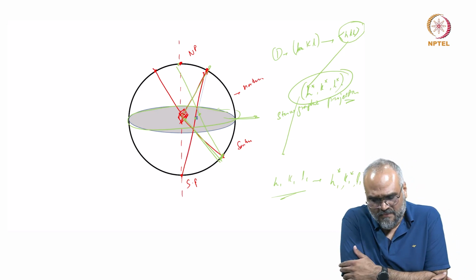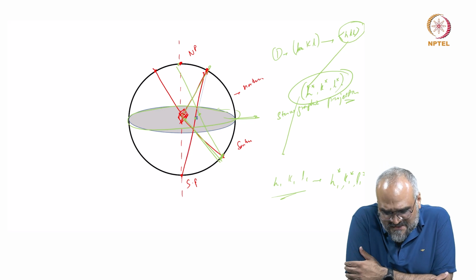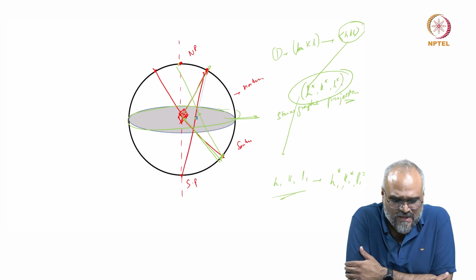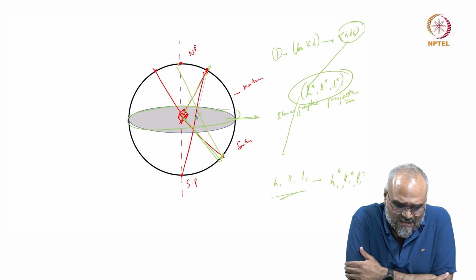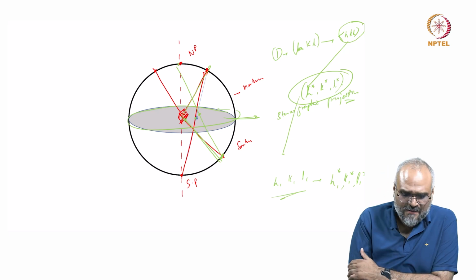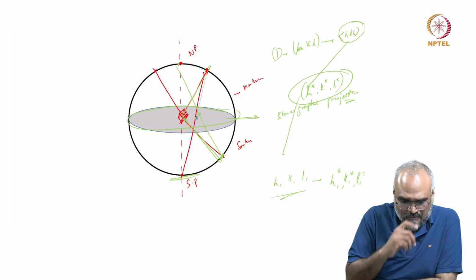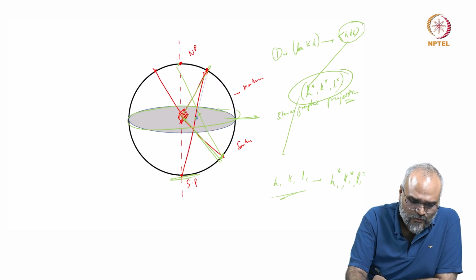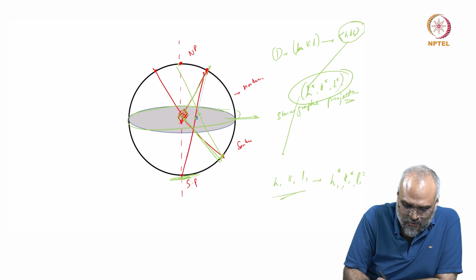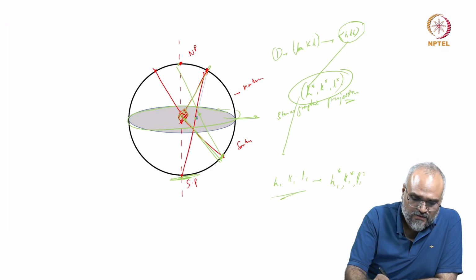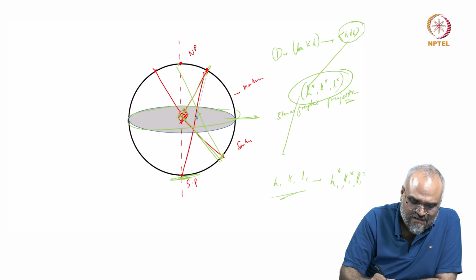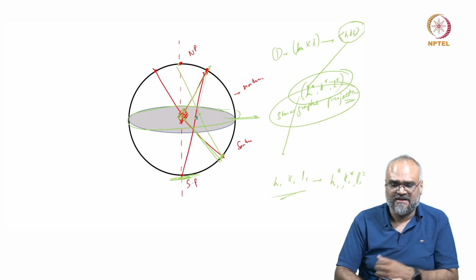And now, if I think of transmission electron microscope as a case where I am recording a diffraction pattern, if I link the position where I am recording the diffraction pattern as somewhat at this plane from a unit cell which is at the position of the specimen, I can actually link the projected spots that I get from a diffraction pattern to the planes that are satisfying the Bragg's law and giving the diffraction pattern through this kind of a relation.